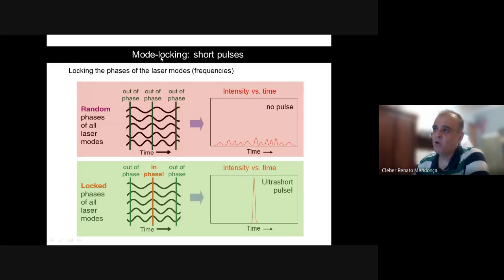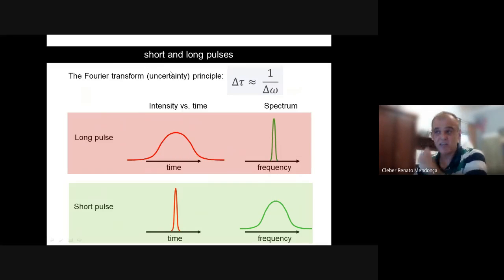But if somehow we are able to lock the relative phases of the longitudinal modes of the cavity, you get interference between the modes in the cavity, and that creates the femtosecond pulses, or the ultra-short pulses. As you can see here, the larger the number of modes, the shorter the ultra-short laser pulses will be, because there is a higher number of modes interfering. So there is a relationship between the pulse duration and the spectrum of the laser pulse, which is basically the Fourier transform or uncertainty principle.